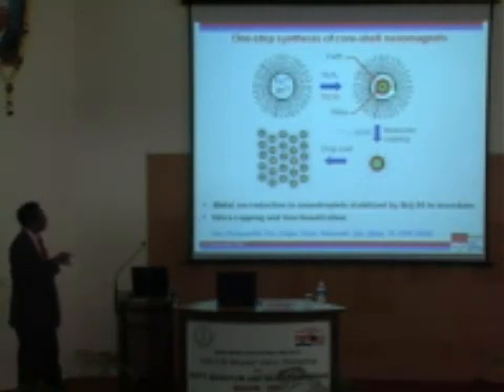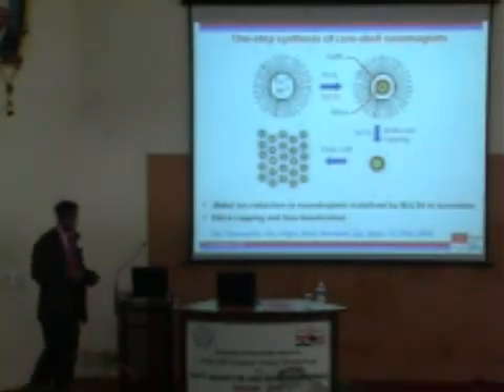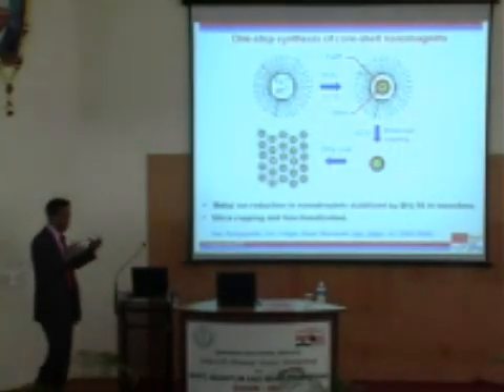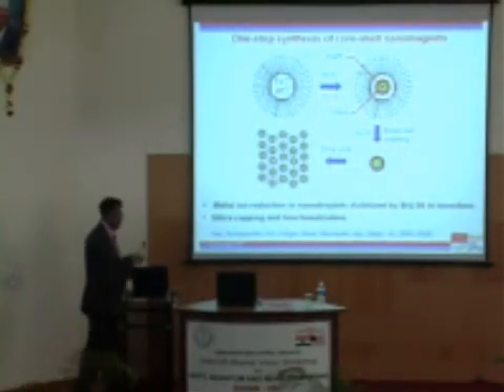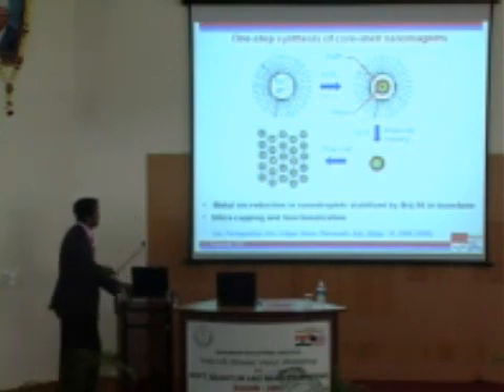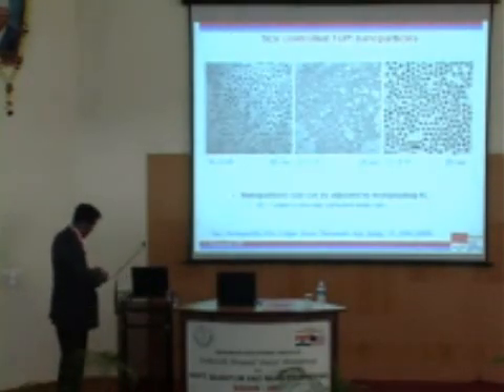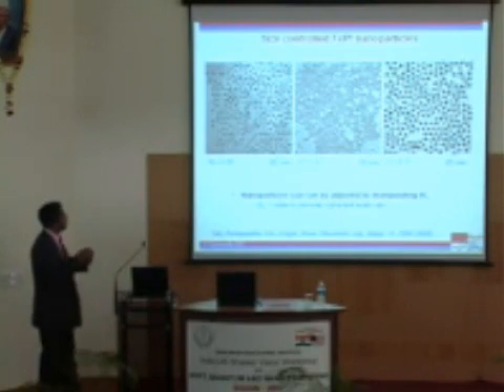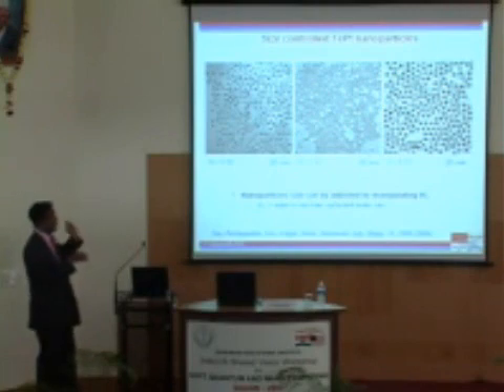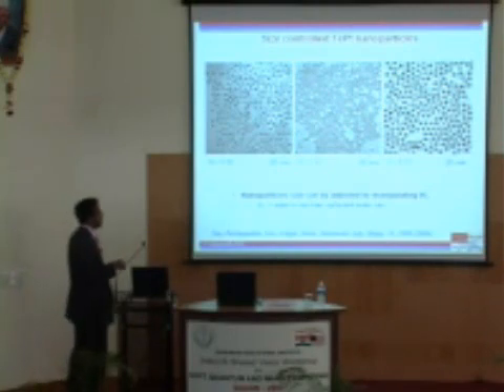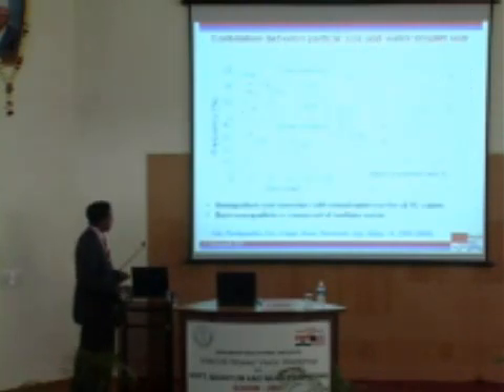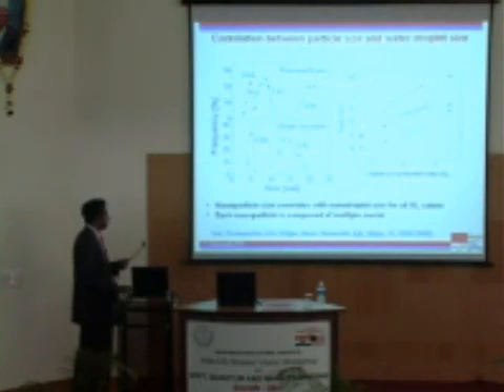And additionally, I can also functionalize the surface with molecules and hence disperse it in other matrices and biological systems, or help it to assemble and get these kinds of structures. This is a cartoon, of course, and this is actually realized, and I'll show you the various aspects of it in the next few minutes. You can see we can control the particle size very beautifully, and none of this is optimized here. We can optimize it and get really great pictures, but the point over here is that you can control the particle size just by adjusting the water droplet size by simple microemulsion chemistry.